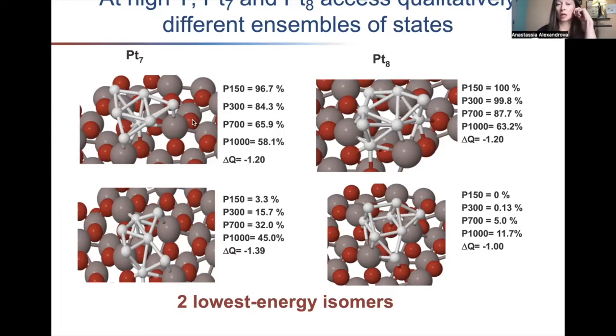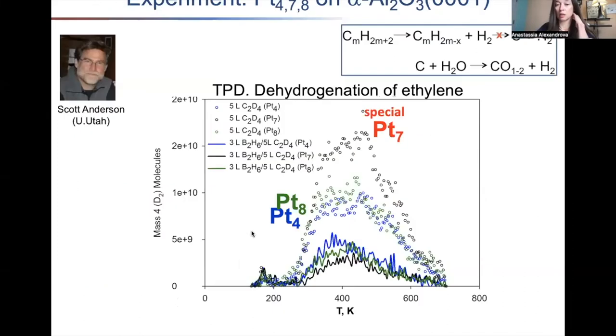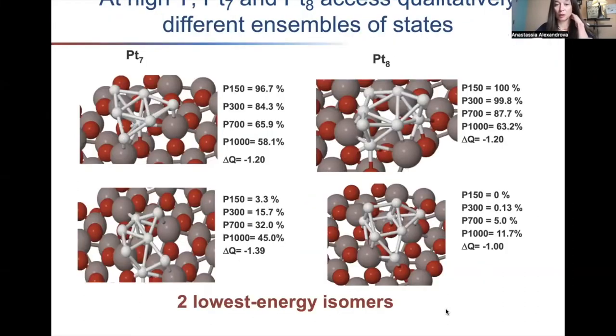However, if we use the paradigm that it's not one cluster form but many that are present under reaction conditions, and start expanding the ensemble toward more states the system can actually populate, we see a divergence. Here, P number is the Boltzmann probability of being occupied at an indicated temperature. At 700 K before any reagents arrive, the global minimum of Pt7 is about 66% of the population — but there is also a fair number of clusters in a flatter form that makes more contacts with the surface.